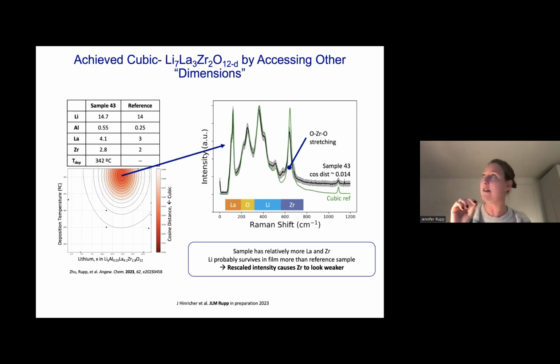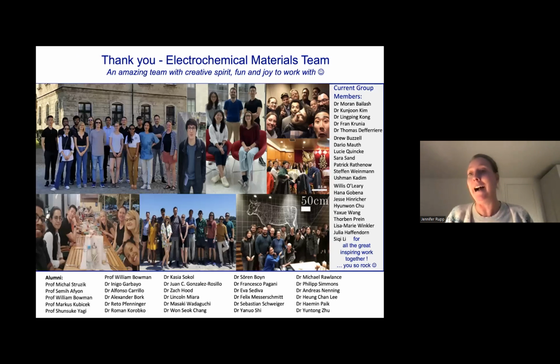So we learn a lot not only about dopants and phase boundaries, and about where to play how much, but we also learn whether we can live in a world where in the future you make a material, take one Raman snapshot, and if it's dense, you could just bring it into the battery, and you don't even measure conductivity because you have already calibrated that before, that it's going to be okay. And that would be a very fast and efficient screening way for industry. I leave you with that thought.